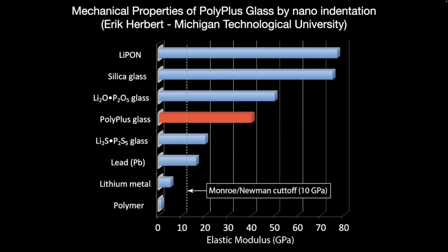And Eric will go into this in more detail, but just a very quick comparison of the elastic modulus of the glass that we're working with in red, versus a polymer electrolyte. Of course, they're very soft materials, and lithium dendrites, as we know, penetrate polymers quite easily, particularly at room temperature. But as you go through these glass moduli, you can see that we're pretty close to the strength of an oxide glass. So these are relatively strong materials, certainly strong enough to repel dendrites.